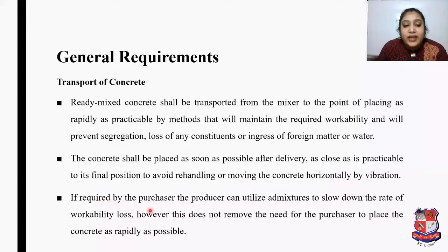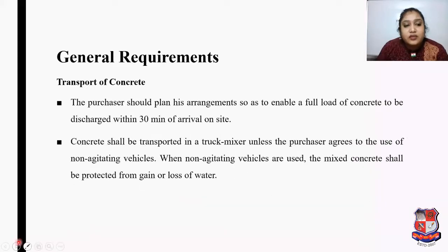If required by the purchaser, the producer can utilize admixture to slow down the rate of workability loss. However, this does not remove the need for the purchaser to place the concrete as rapidly as possible. The purchaser should plan his arrangement so as to enable a full load of concrete to be discharged within 30 minutes of arrival on site.